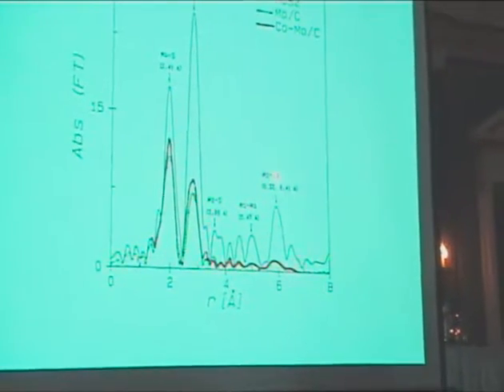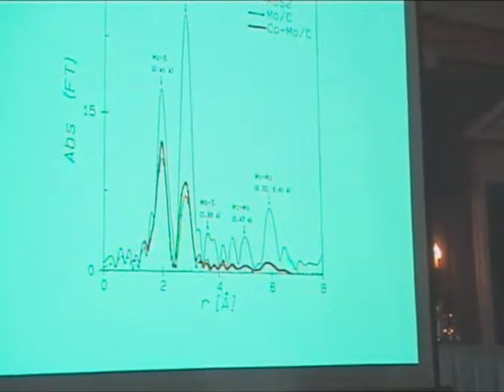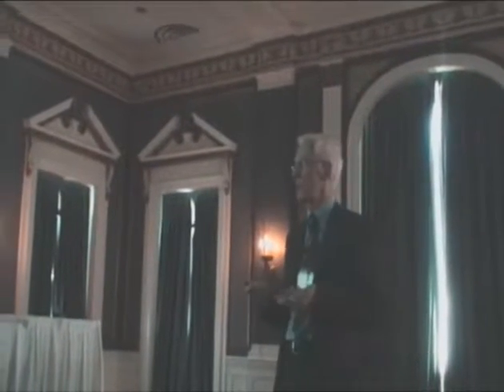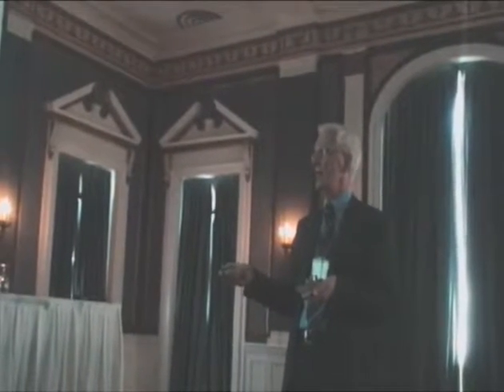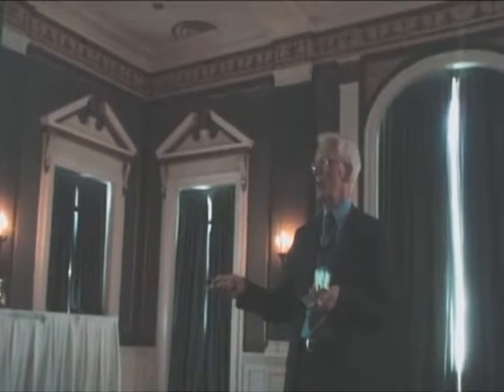And this is also called forward scattering, because the electron goes out, goes to the molybdenum neighbor, and continues to go to the second neighbor, forward, and then it's back scattering. So it's called forward scattering. And that's why its intensity is larger than any intensity in between.